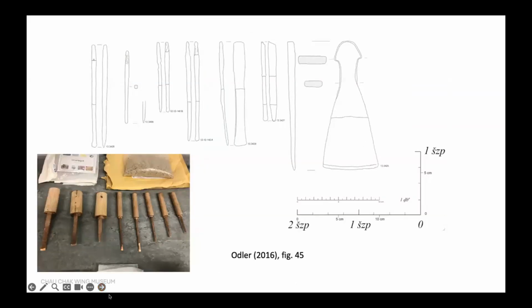Now, this particular set was recreated from the forms of surviving examples from the late 6th dynasty copper tool blades found in Giza tomb G2381, shaft Z, and are chronologically close to the production of the false door in question. The replica tool blades were made of an alloy consisting of 4.5% tin and 95.5% copper.